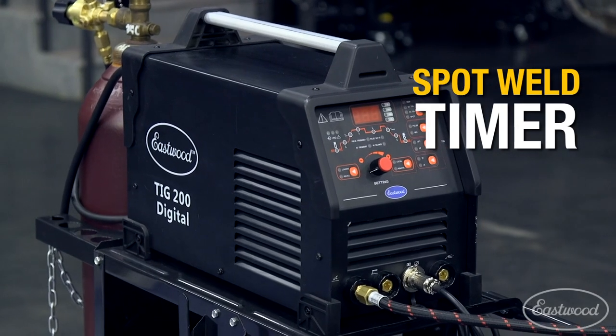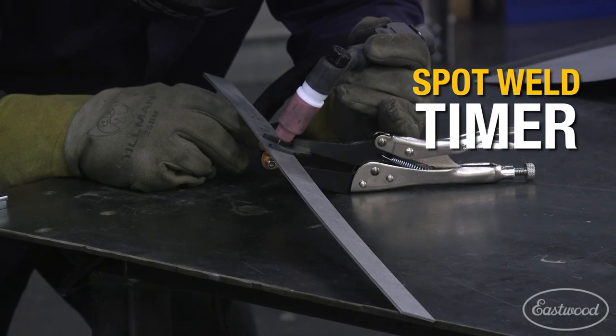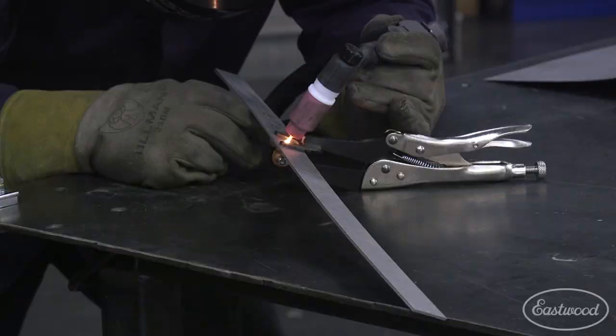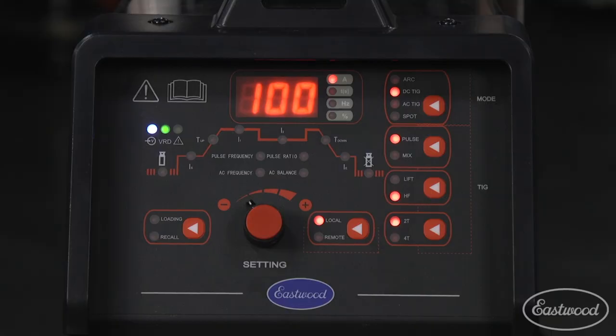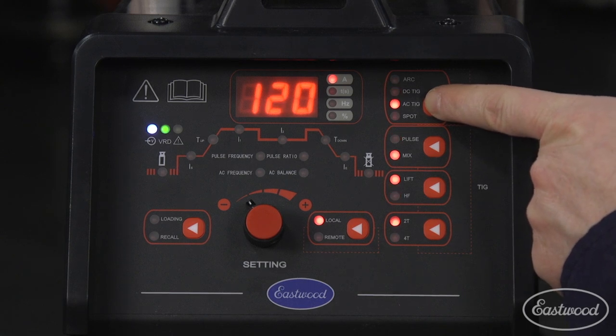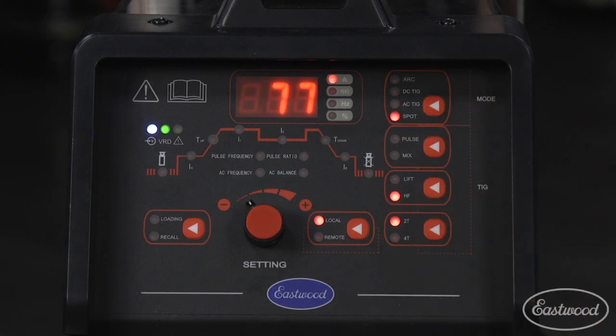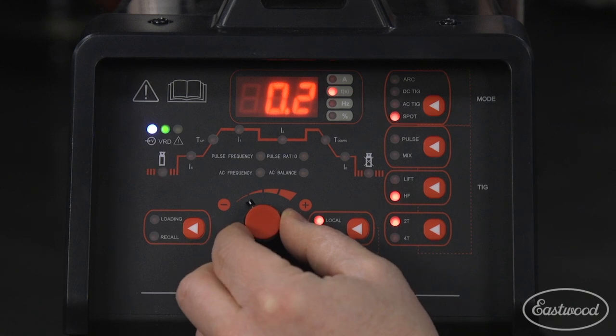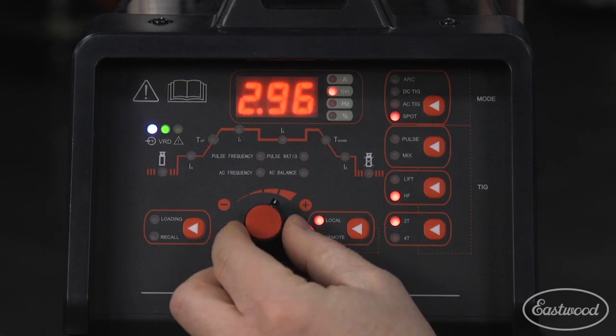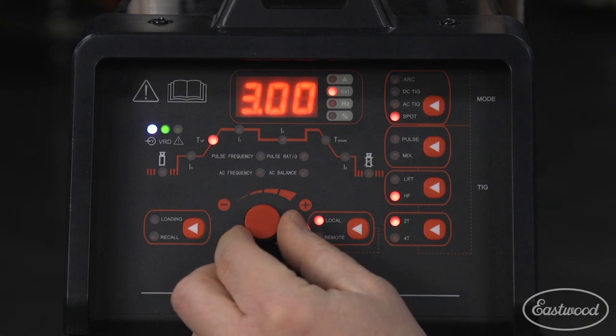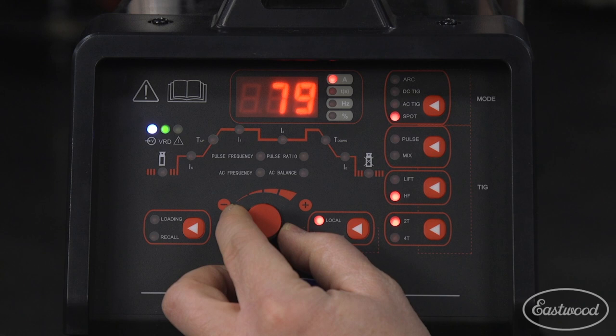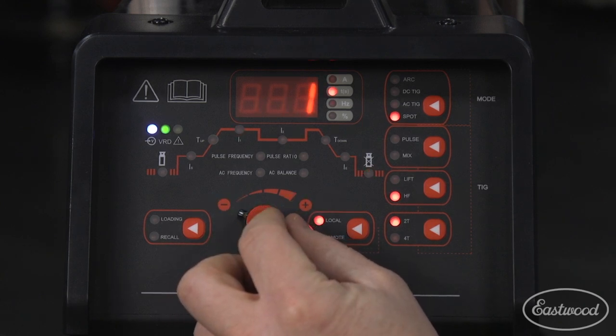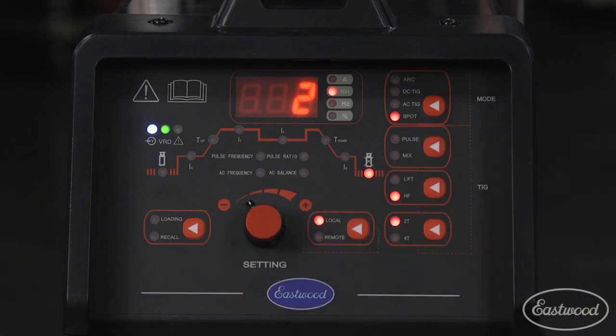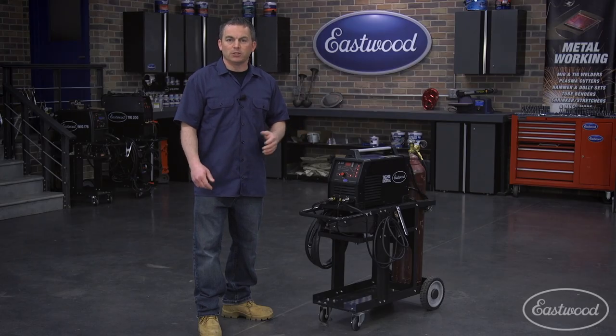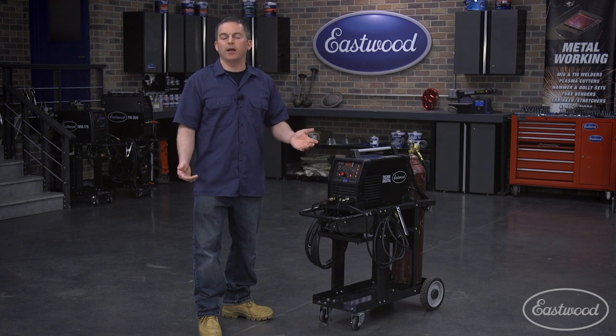Now let's move on to the spot weld timer. Spot weld timer is great for spot welds, plug welds, or for running short beads and can be programmed from 0 to 5 seconds. First, select the spot weld option. When it's selected, the machine will automatically be set to high frequency and 2T. Now set the pre-flow time. Then program the amount of time you want to weld. We're selecting 3 seconds. Then set the amperage you want to weld, which is 80 amps for this material. Then select the post-flow time. Now you're ready to start spot welding, making the same quality welds every time with the Eastwood Digital TIG. Simply pull the trigger and the machine will weld for the programmed time before stopping. Pull the trigger again to repeat.